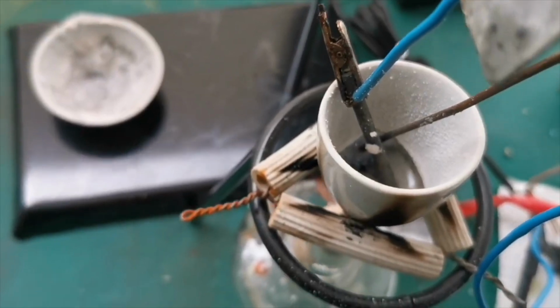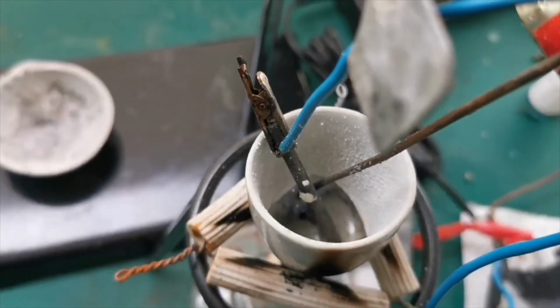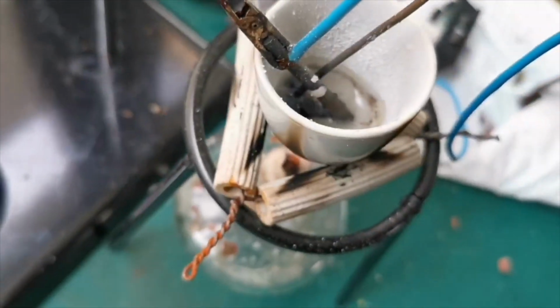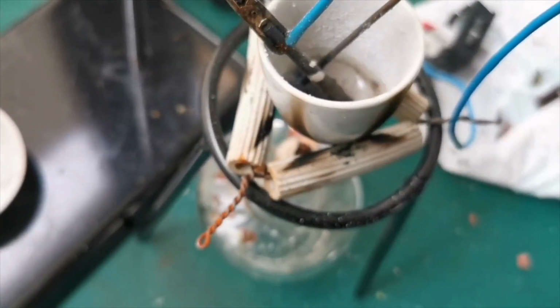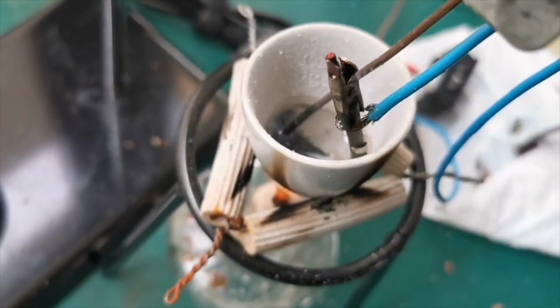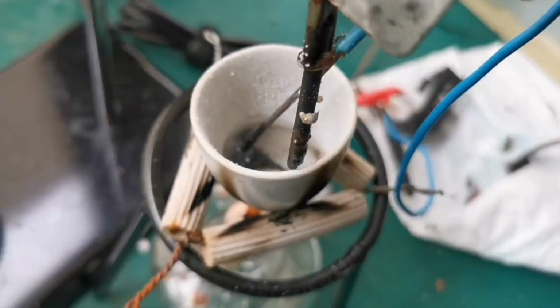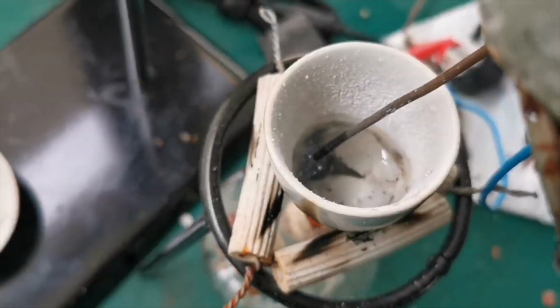Notice that the blue color appeared again, this time much more vividly. In this shot, you can clearly see the blue color appears to travel from the cathode to the anode. When I took the anode out, there are clearly a lot of molten lithium globules floating on the melt.